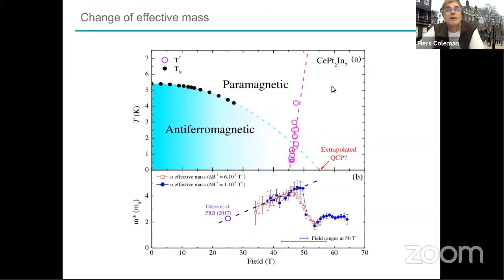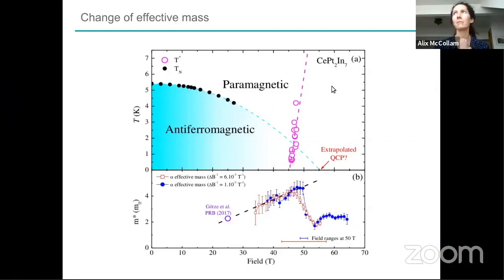And has the spin susceptibility been measured under pressure? No. So NMR was done, and transport has been done. We've tried to do tunnel diode measurements, which would give you some kind of hybrid of resistivity and susceptibility, but the quantum oscillations disappear under pressure when we try to do the tunnel diode measurements. So that hasn't been successful, at least not yet.